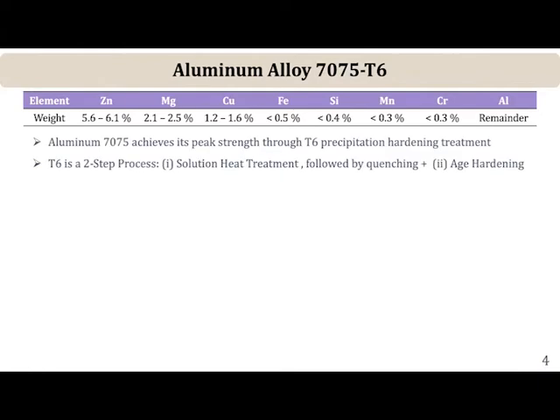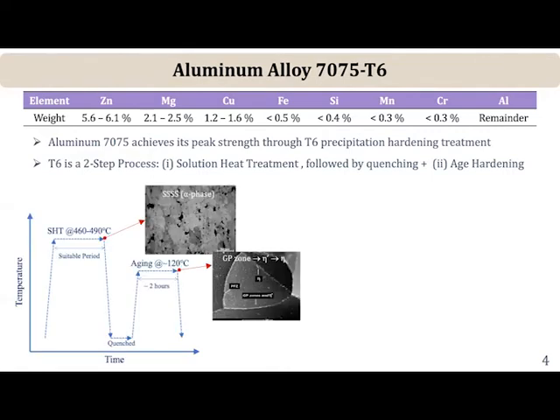Okay, so basically it's an aluminum zinc magnesium alloy with about 5.5 to 6% zinc, 2% or so magnesium and copper. These are the main strengthening agents or alloying elements. And it achieves its high strength due to the T6 treatment, which is a peak-aged condition. So basically the alloy is solution treated, typically around 460 to 490, it's quenched and then aged at 120 degrees C. So basically this alloy derives its strength through precipitation.